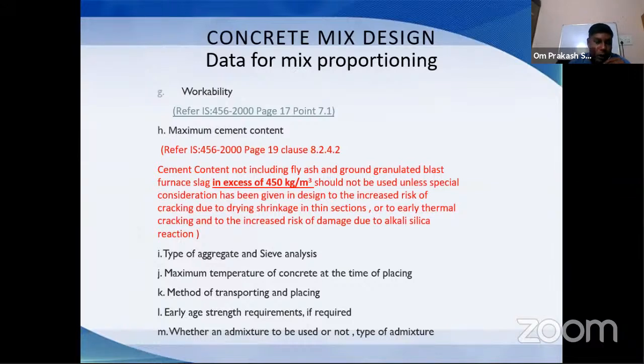What will happen if we use a higher content of cement? If we use a higher content of cement, it will give high heat in the mix, due to which drying shrinkage and early thermal cracks will happen in the concrete, or in a later stage cracks may also form in the concrete, which will ultimately harm the durability of the concrete. Again, what kind of aggregate we are using, we must know, and sieve analysis of the aggregate we must know, as we discussed earlier. Maximum temperature of the concrete